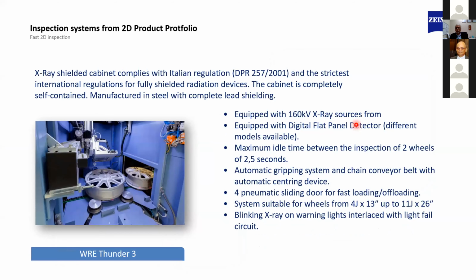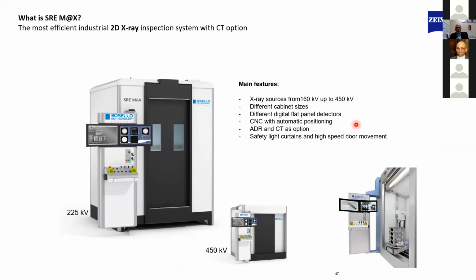So just to give you an idea how fast these components are getting measured, within the cycle time of 30 to 35 seconds. And the power source can go from 160 kV to 450 kV. So for example, for aluminum, 160 to 225 kV we can accommodate, but 450 kV is basically for high-density material, steel or iron casting; they normally go for 450 kV.